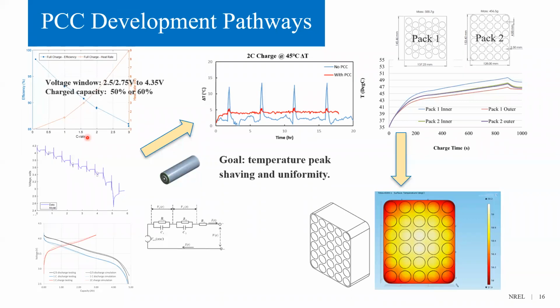Besides the C-rate, there are other charging parameters evaluated, such as charging voltage windows and expected capacity. Also, a two-resistor capacitor equivalent circuit model was then developed and validated. The model works for both load cycles and constant rate loadings, providing enough accuracy in estimating not only battery electrical response, but thermal response. This result has been used for PCC design optimization at AllCell. The prototype design here is an optimized outcome.